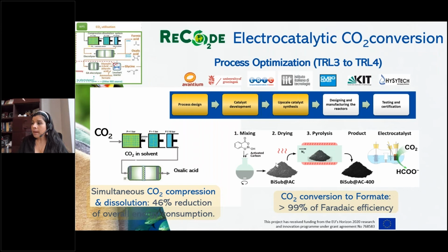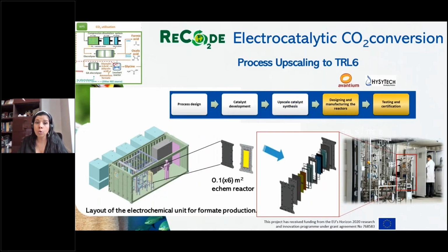We have also optimized the catalysts that have been employed and will be employed in our electrocatalytic reactors. For example, here you see the catalyst for the conversion of the CO2 to formate that has a Faradaic efficiency higher than 99% and is based on bismuth, so based on non-noble metals. And here you see our TRL 6 plant that will be constituted by a stack of electrocatalytic reactors with an electrode size of 0.1 square meter.